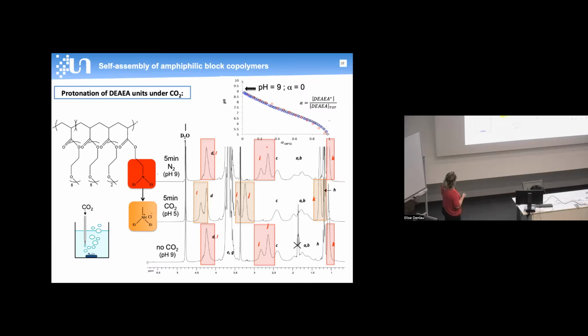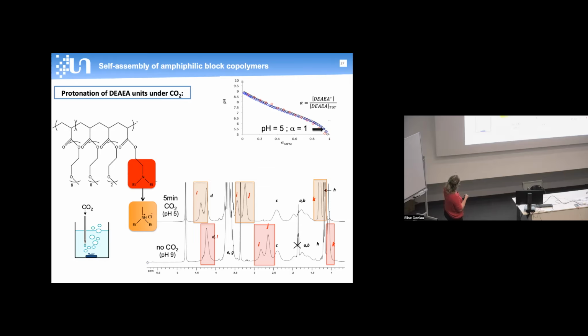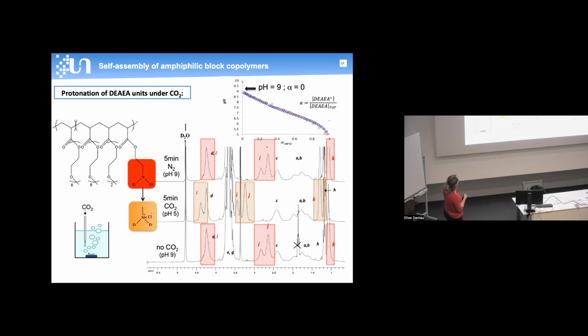And the protonation of the amine with carbon dioxide was also followed by titration, here at the right of the slide, showing that after 5 minutes bubbling, the pH corresponds to an ionization degree of 1, total ionization degree, and after 5 minutes nitrogen, the pH corresponds to the neutral form of the amine.